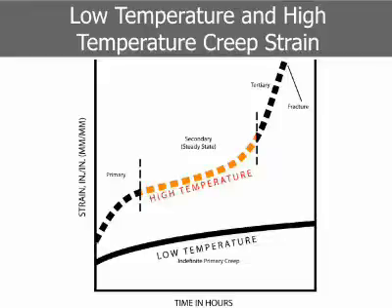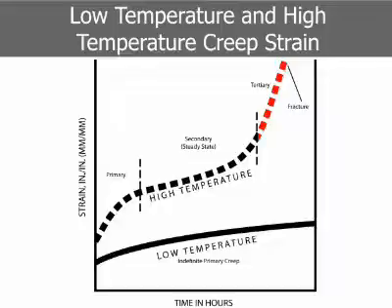There is no loss of strength during the primary and secondary phases. The tertiary phase begins when the rate starts to increase. Its progress is comparatively rapid, and the rate continues to increase. The material loses strength during this phase until it permanently changes shape and failure occurs.